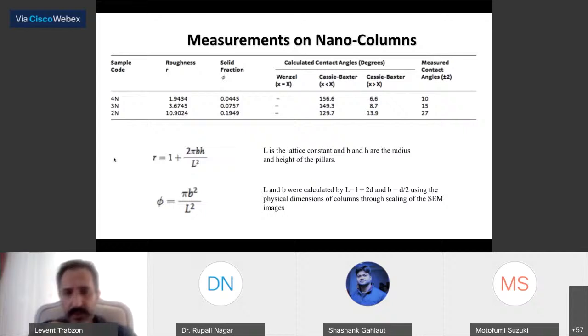Depending on what kind of models or approach, as it is well known, there are 2 well-known models. One of them is Wenzel, the other one the Cassie-Baxter model. But to understand which model fits well to our experimental results, in the experimental measurements, we measure contact angles on the surface. You see, for 4N, we got 10 degrees, 3N 15, and 2N 27 degrees. And we also calculated based on the Cassie-Baxter and the Wenzel models to compare with the experimental result.